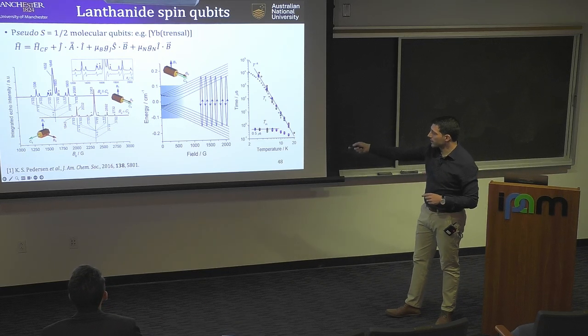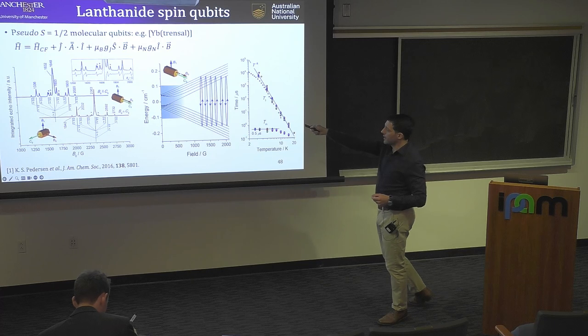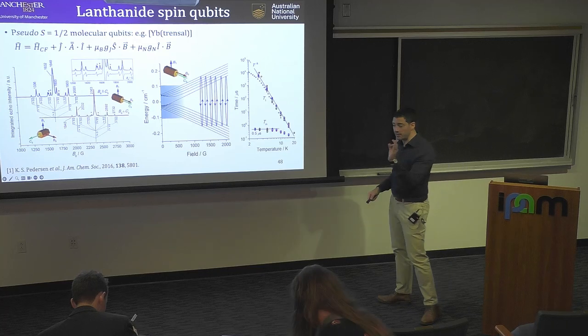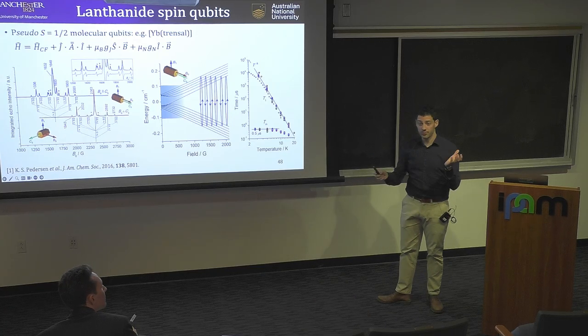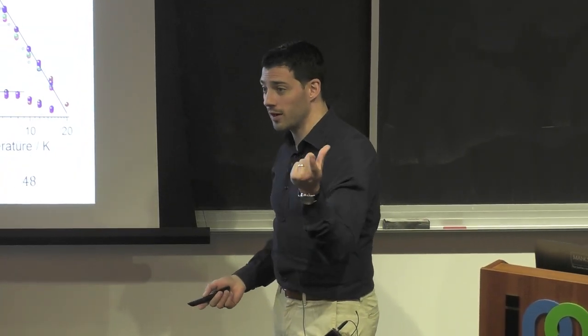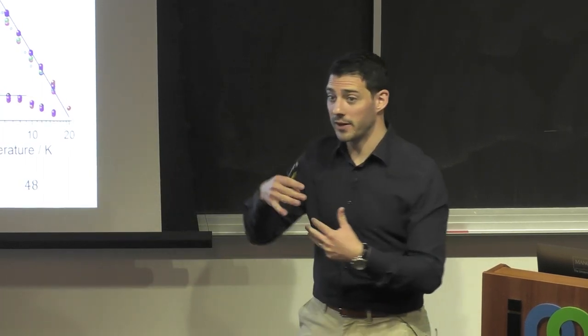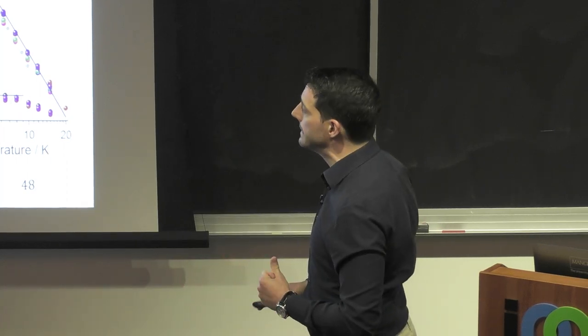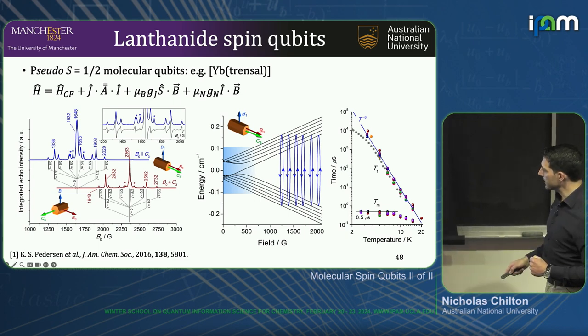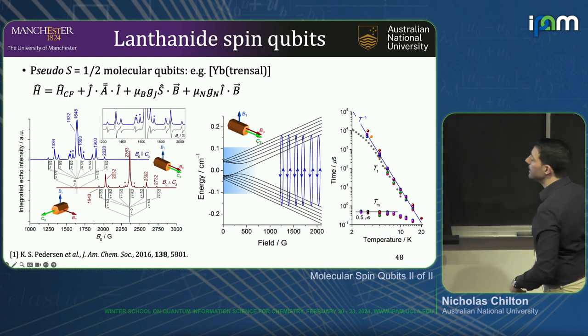You get all these beautiful lines as a function of magnetic field, but of course they're anisotropic — it depends on the orientation of the magnetic field. With B0 along the C3 axis of the crystallite, you get a particular splitting. These crystals actually grow like pencils — long rods with hexagonal sides — so you can very easily do a single crystal experiment. They're air-stable and luminescent, so you can shine UV light on them to find where all the crystal field levels are.